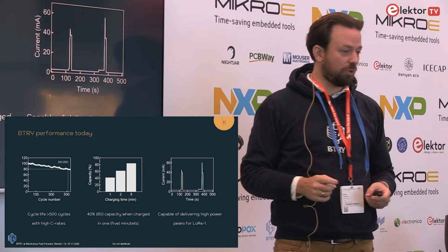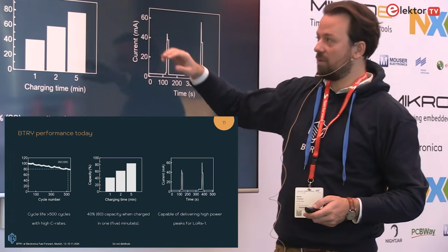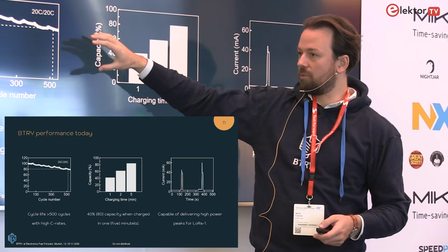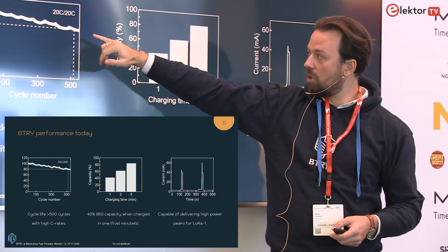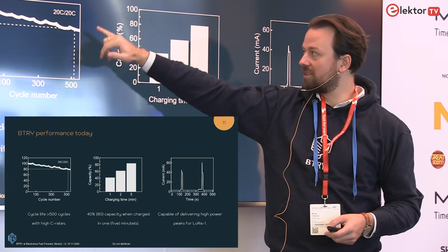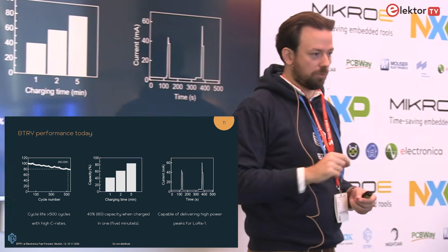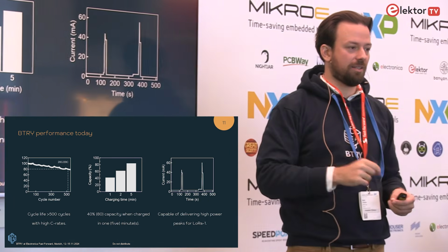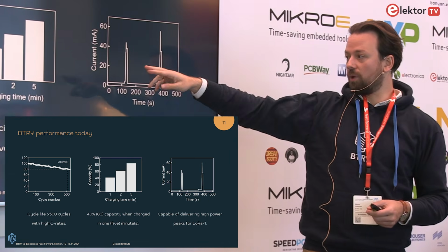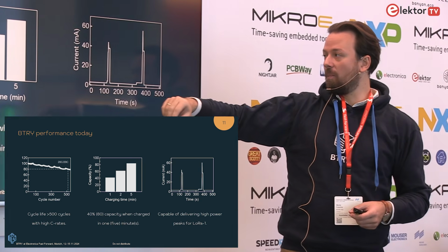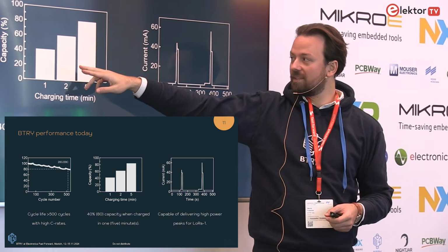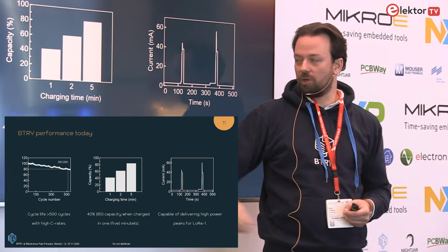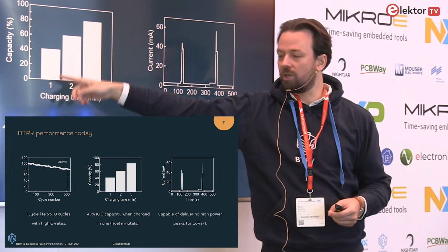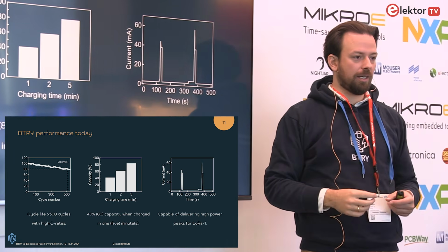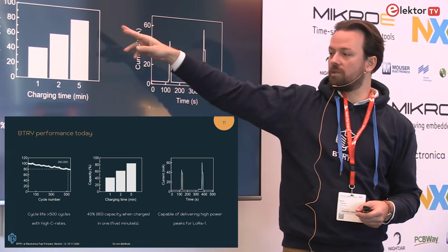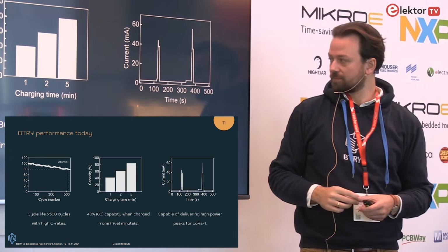How does it perform today? You can see results from our cells where we are at 500 cycles if we cycle at 20 C, so 3 minutes charging and discharging, a very fast charging and discharging rate. We can charge in 1 minute, not to full capacity, but we already get 40% of the full capacity inside of these batteries. And if we had 5 minutes, we're above 80%.